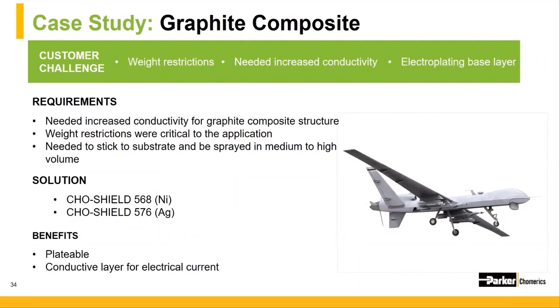They used an electrically conductive coating as a seed layer for electroplating, as well as to increase the electrical conductivity. Slightly related to this application is this process used within other industries, such as the automotive aftermarket. A conductive coating was applied as part of a multi-step process for custom chrome parts, and was actually able to reduce the number of stages that were required for that plating process.